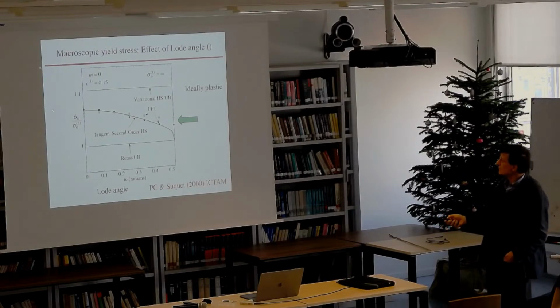These are some numerical results that show the dependence on the Lode angle. This is an old method, the tangent second order method, which gave pretty good results for axisymmetric, but down here went down to the Reuss lower bound, so it was below the predictions of the FFT.